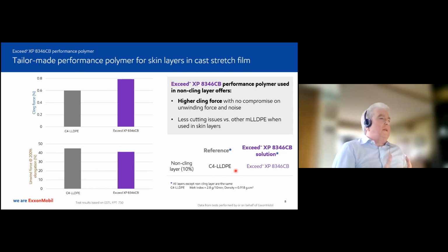Now, the other important significance of looking at C4 as the reference here is that in many cases, metallocene skins are difficult to cut on lines. And so we found that using the Exceed XP8346 in the non-cling layer actually is not so bad on cutting. It's fairly forgiving. So in combination with its easy processing, the fact that it promotes cling in the non-cling layer, reduces unwinding force, and has terrific puncture resistance, particularly when used as a discrete layer, this is a very exciting new grade that the cast stretch customers are now having a good look at.